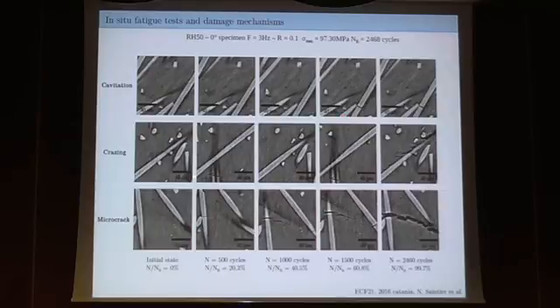It doesn't seem to be very critical, but you will see after that it has a role in the other mechanisms. Crazing was also observed to appear. You can see here next to the fiber, small cracking, which is really similar to what we could observe as crazing. And you can see maybe that before crazing, you have small cavitation next to the interface between the fiber and the matrix. So cavitation is a preliminary mechanism to other mechanisms, such as crazing.